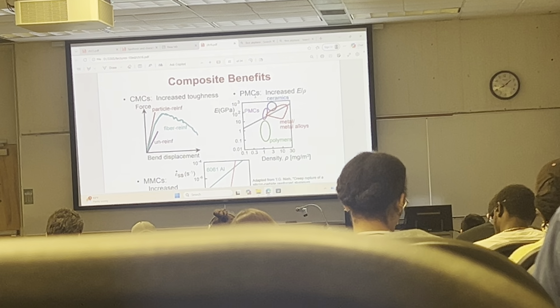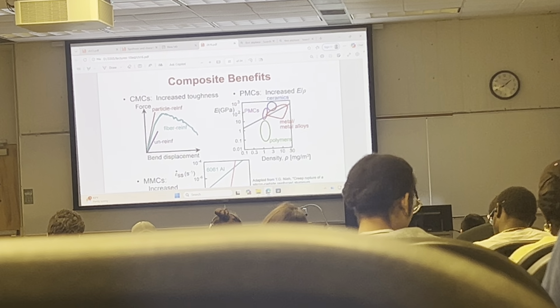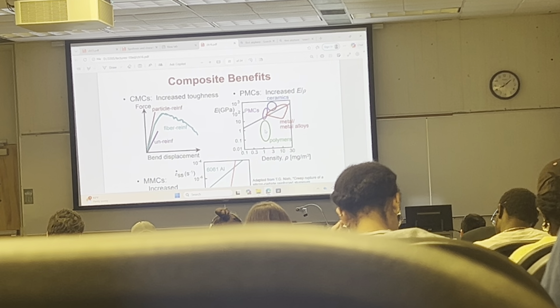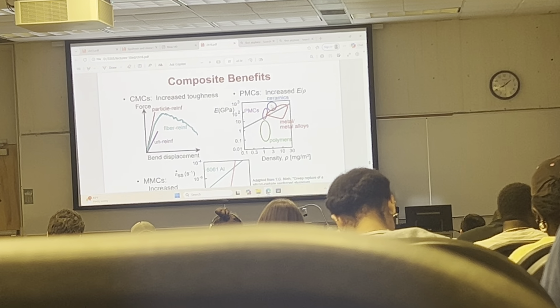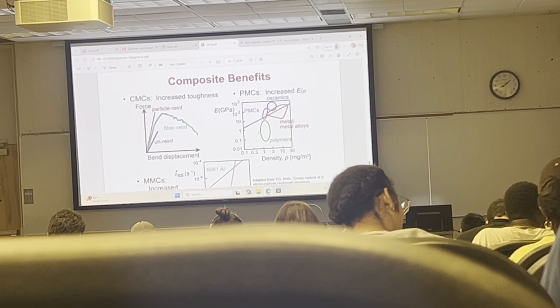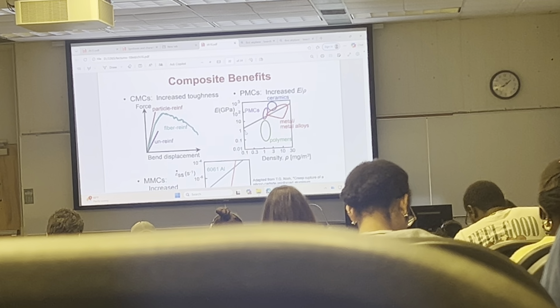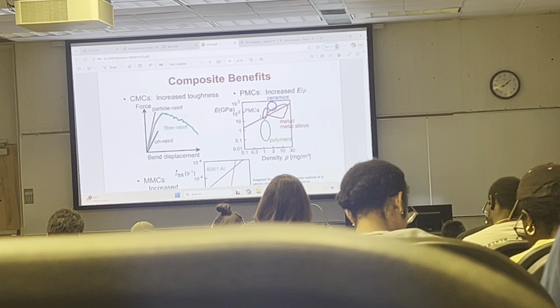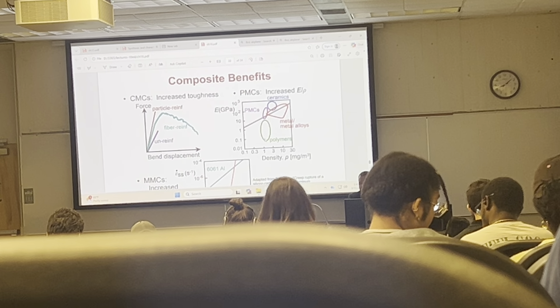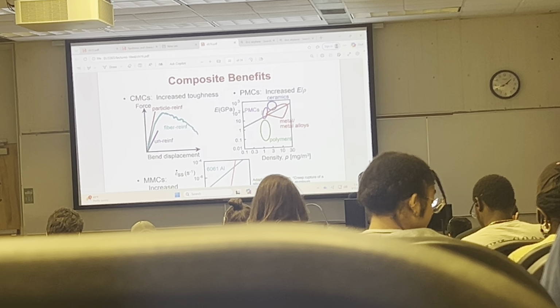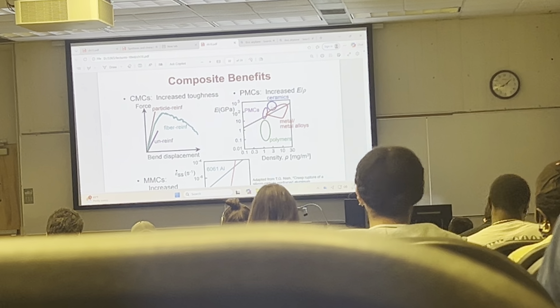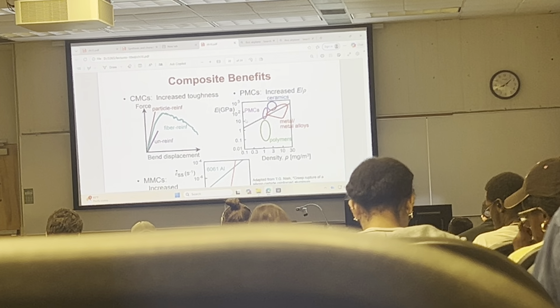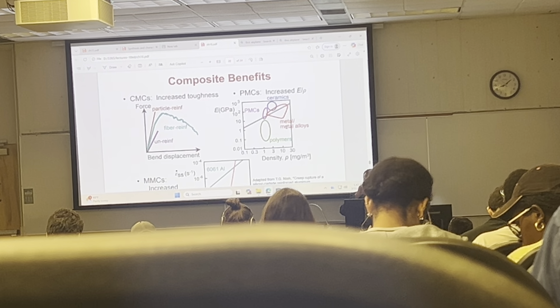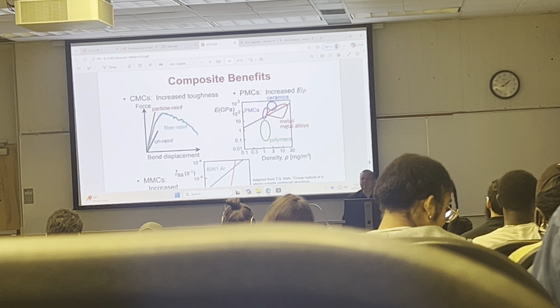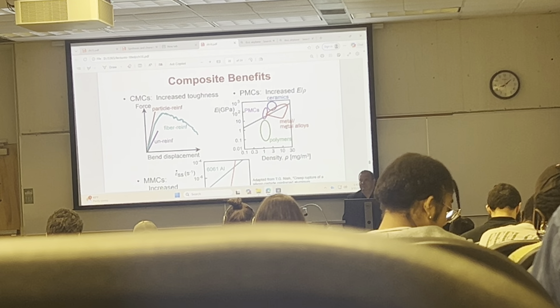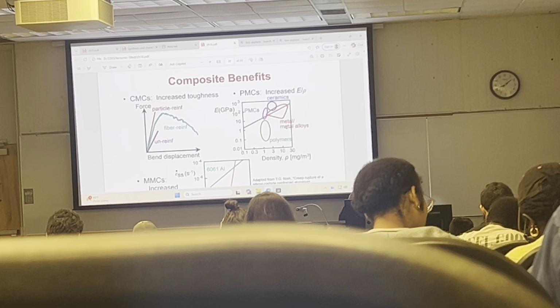And here's an example of polymer matrix composites, elastic modulus versus density. Polymers, metals and alloys, and ceramics. So you see polymers are here, low elastic modulus. You combine this with some sort of reinforcement, and you're pushing this whole class of materials to a higher performance that can outperform metals and ceramics almost, in terms of the ratio of the elastic modulus to the density. So this is a very important slide that summarizes the idea of reinforcement of the composites, depending on what kind of matrix it is.